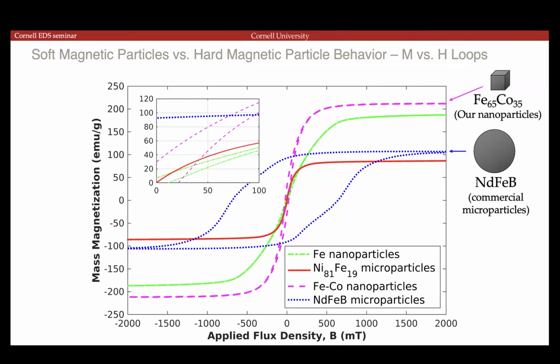Yeah. The only thing I'm concerned about is we haven't considered other loss mechanisms, like eddy current losses. If the material is highly conductive, then you have not just this loss, but also eddy currents, although I presume those are accounted for here, because depending on what frequency this was measured at, they may or may not be. Is this at very low frequency? Yeah, very low frequency. If you go to higher frequencies, these curves will potentially further expand, because now you have eddy currents induced in the material, which will also show up on your BH measurement equipment as a widening of this loop.